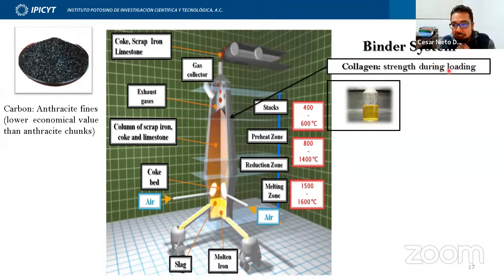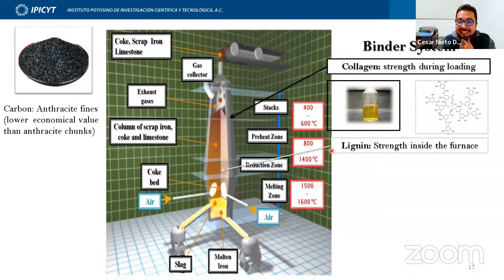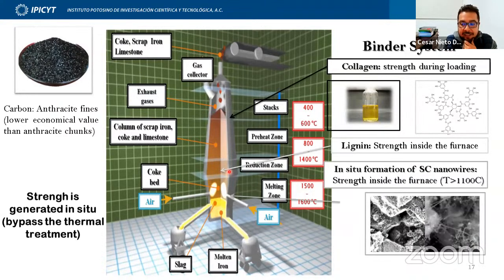But anyway, we decided to use collagen as the first binder to provide strength to the briquette before it's loaded into the furnace. The second binder that we used was lignin, and lignin will provide the strength in the preheat zone, or mid-temperature zone. Then we add to the formulation silicon metal, silicon with oxidation state of 0. In the conditions inside the furnace, silicon carbide nanowires are formed. These silicon carbide nanowires connect all the carbon fraction in the anthracite briquette and allow the carbon briquette to survive all the way down the furnace.